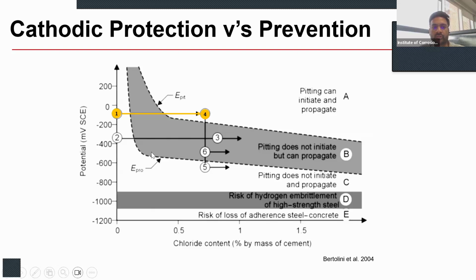So the idea behind a cathodic protection system is to bring down the potentials to more negative values, either to zone B, where pitting does not initiate but can propagate, or zone C, where pitting does not initiate at all and does not propagate—meaning passivation is reached.